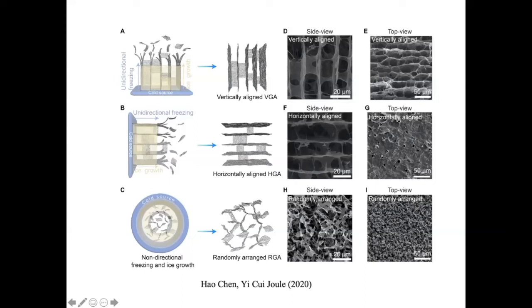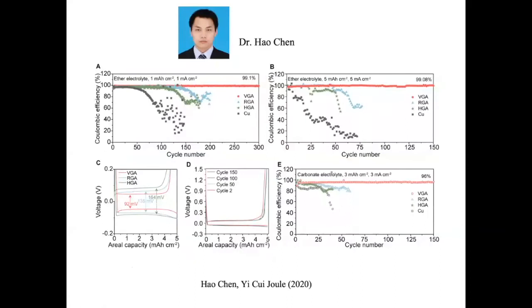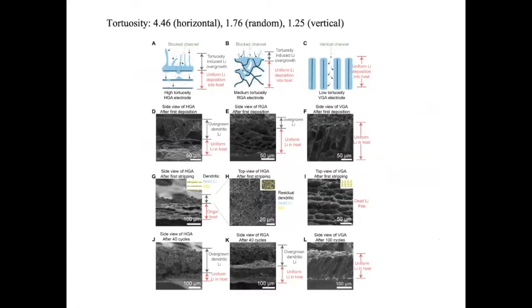So this is a comparison of three different tortuosities. And it's very clear the vertically aligned one has low tortuosity and gives you much more stable cycling. Look at figure A right here: vertically aligned graphene is the most stable in coulombic efficiency, the deposition is more uniform, followed by the random graphene, and then followed by horizontally aligned graphene. It's a very clear effect right here. And this tortuosity difference: horizontally aligned is about 4.5, random is about 1.8, and vertically aligned is about 1.2, 1.3.